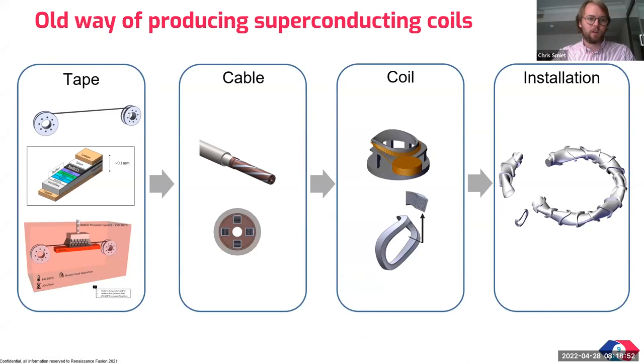Well, let's first look at how traditionally, there hasn't been a high temperature superconductor stellarator built yet. But how would one do that with these new HTS tapes? So these come in a very long strand of superconductor deposited on Hastelloy, with many, many buffer layers in between. And these are quite finicky. If you bend them too much, then the critical current goes down. And about 6 machines are needed in order to put all of these layers in the right order.